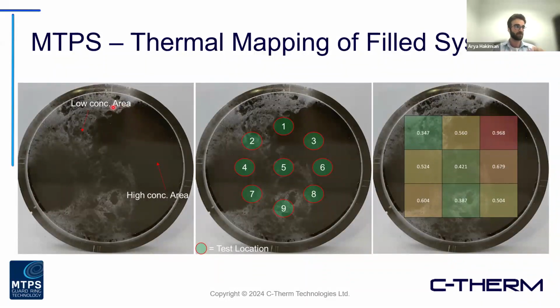Now, this example here is quite exaggerated, but just to show the point, there is a conductive filler added into this polymer matrix, very non-uniform. You can tell that just by looking at it, right? But one of the unique things with the MTPS, related to the fact that it's a single-sided interface, is we can actually take the sensor and move it around to different locations on your material, if you're dealing with a larger sample, and do these spot measurements.